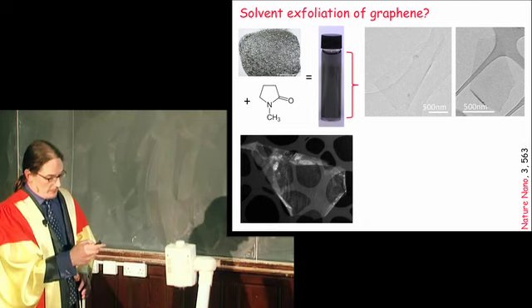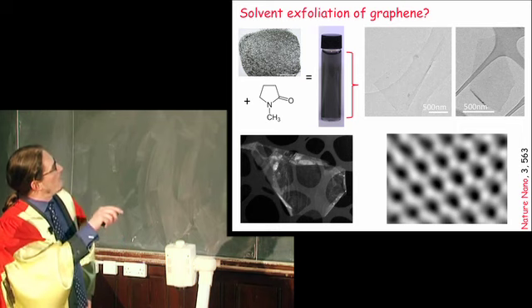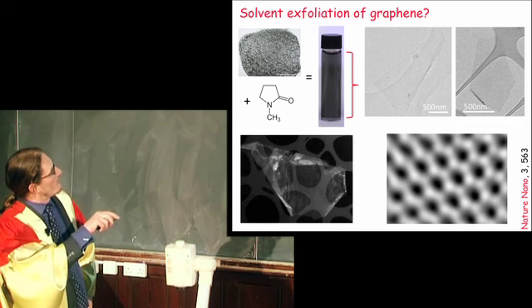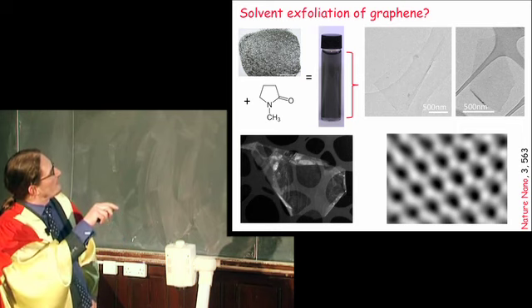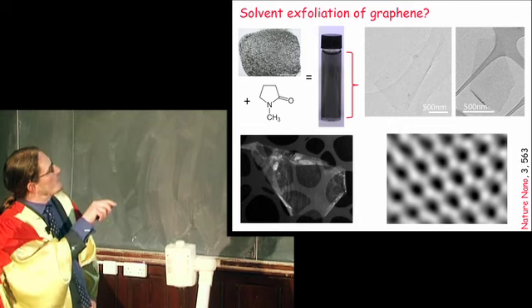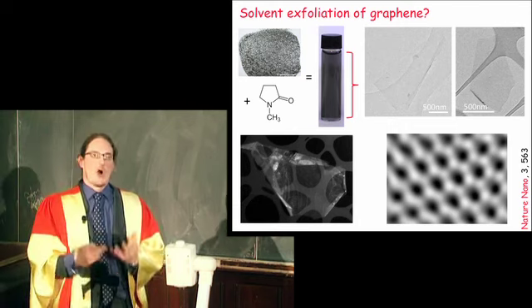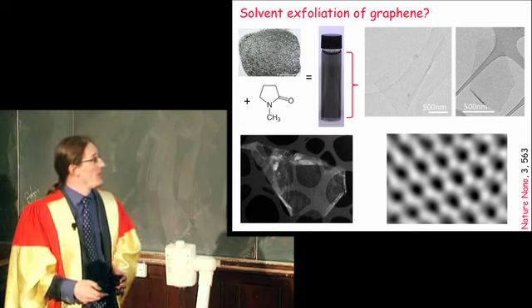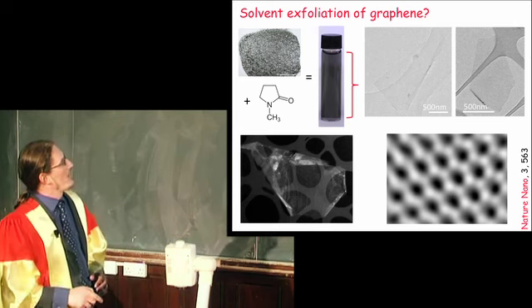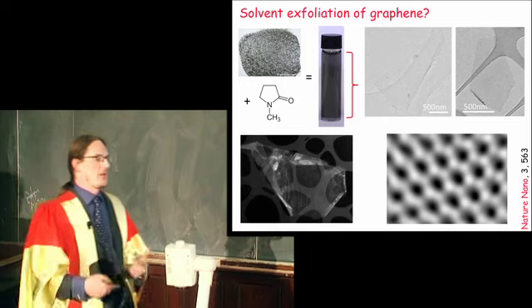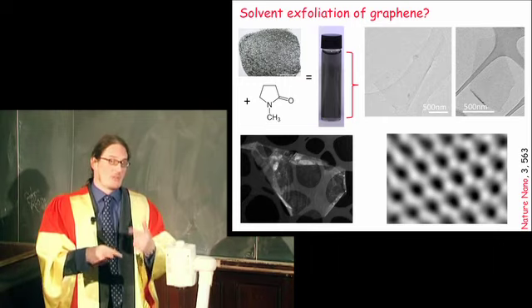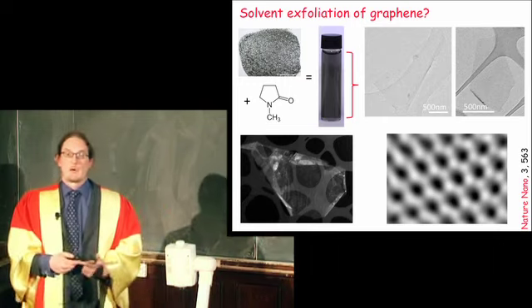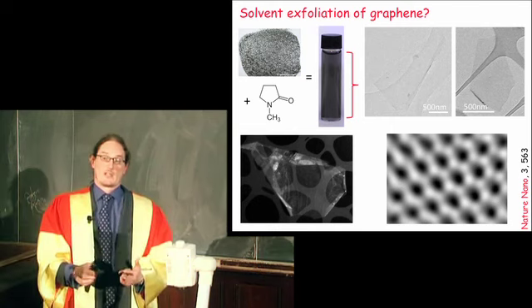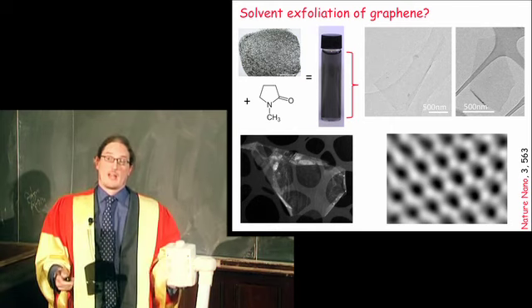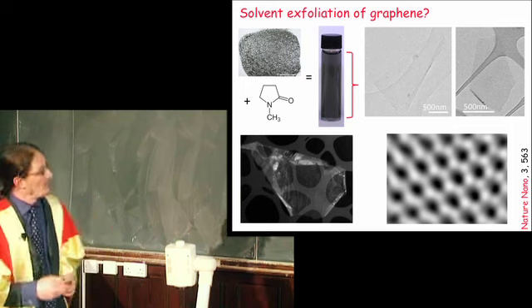You can also look at something called a dark field image, and this is quite nice. It's a nice image. It really shows how thin these things are, but interestingly, it shows that the edges roll up just like old paper that's been sitting in the sun. And the reason I thought this was interesting is that after we got this image, a paper came out in Nature showing that actually the curling of the edges of paper is a scale-free phenomenon and should occur at all length scales. So I thought that was quite interesting.